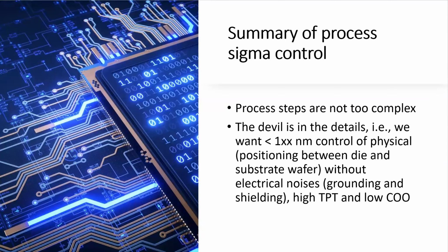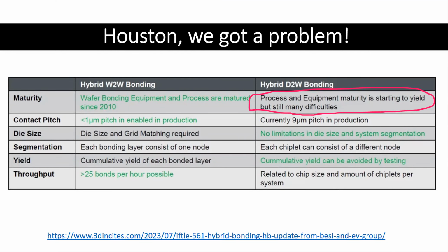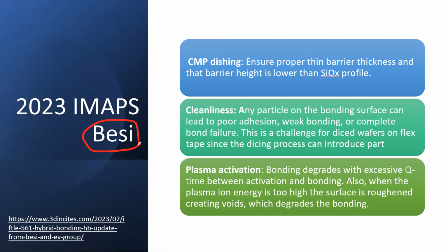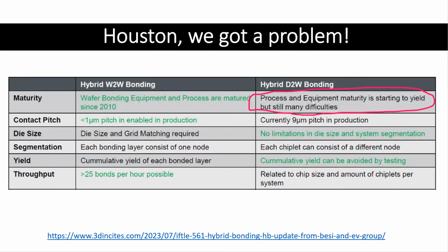Before we go, I forgot to mention this one. Houston, we've got a problem. This is Besi in the IMAPS meeting, which I mentioned earlier. This is Besi's summary. They talk about difficulties, right? This is Besi's perspective. If you look at the other one, their problem is probably very obvious. They say their wafer to wafer bonding is pretty good, mature. They could do one micron pitch, fine. And then die to wafer bonding, they've got a problem. Process equipment maturity is starting to yield, but still many difficulties. And they could do 9 micron. This means 9 micron is pretty okay, but anything less than that, they have problems.